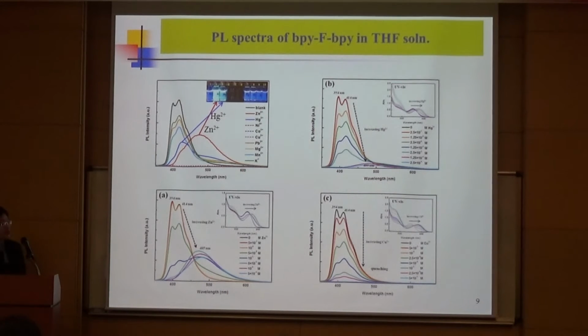We'll first investigate the intrinsic sensing performance for this fluorescent sensing compound in organic solvent. After binding with different types of metal ions in assessed amount, we observe three typical fluorescence responses. First, partial fluorescent quenching without any shift in spectra. Second, partial fluorescence quenching with red shift in emission maxima. Third, complete fluorescence quenching. So in order to get a clearer idea, we chose three different metal ions to study the fluorescent titration behaviors.